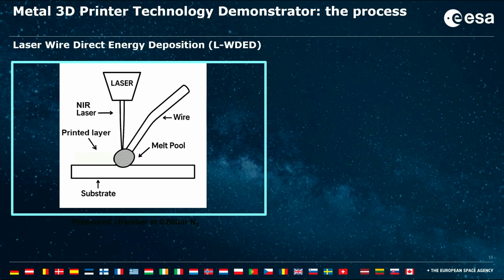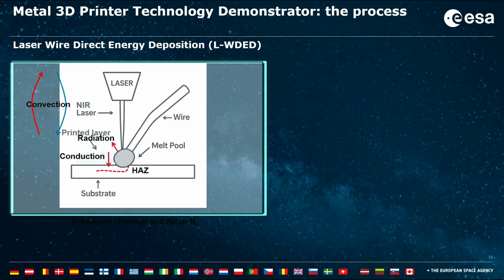So the way it works is that you have a laser which basically shines on a substrate, a metallic plate, and creates a hot zone. And you put a metallic wire into this hot zone, so it creates a melt pool, a pool of liquid metal. And then you can scan the surface to draw a 2D pattern. And if you repeat it layer by layer, you get your 3D printed part.